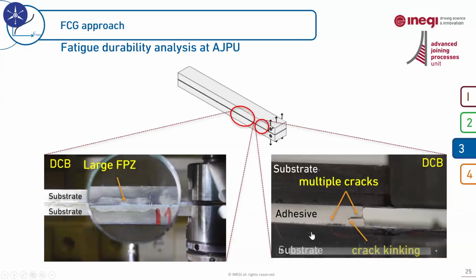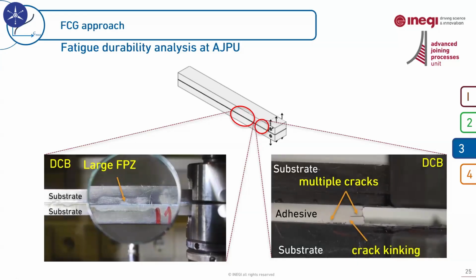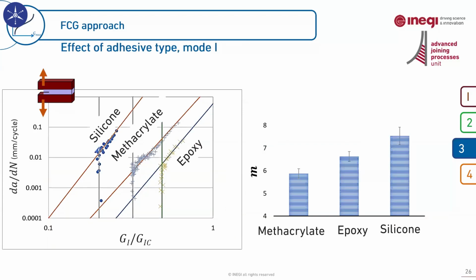So we have multiple cracking, multiple site cracking phenomena here. And that's why fatigue crack propagation analysis and characterization of adhesives in terms of crack growth is really a challenging task if you want to take into account correctly all these phenomena. We have actually analyzed fatigue crack growth in different types of adhesives: silicone, epoxies, methacrylate.